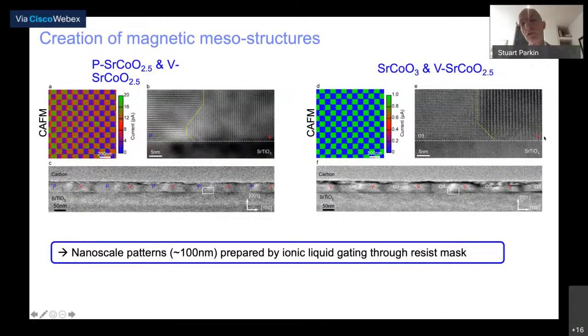On the right-hand side, we've created structures formed from the ferromagnetic metal, shown in green, and the insulating antiferromagnet, in blue. So we can create a whole series of novel spin textures in this way, we believe down to a scale of about 10 nanometers in size.